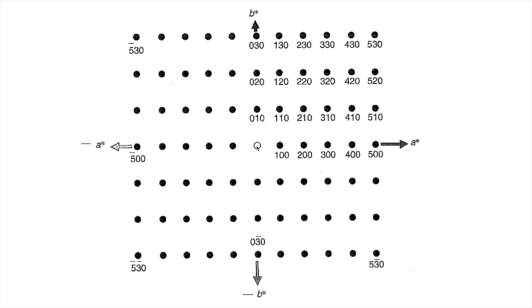So again, since the vector is normal to the HKL plane in real space, it gives us an idea of orientation. And the length of that vector, from the origin to the point, is telling us about the spacing between consecutive planes, right?